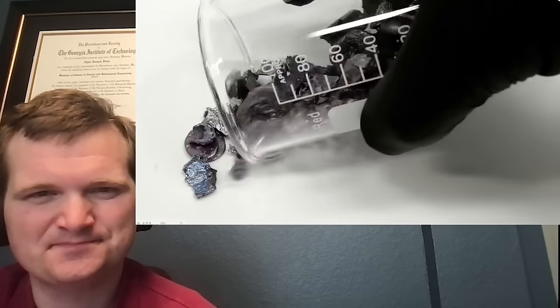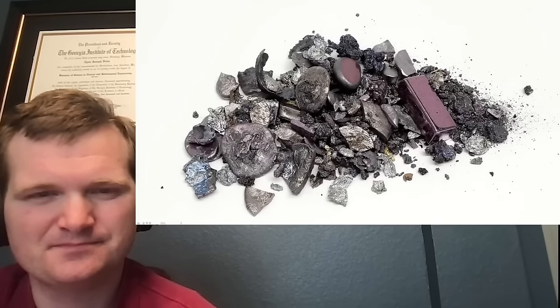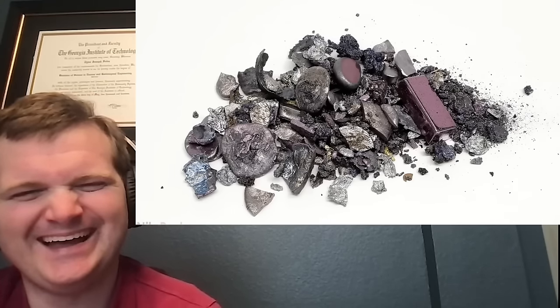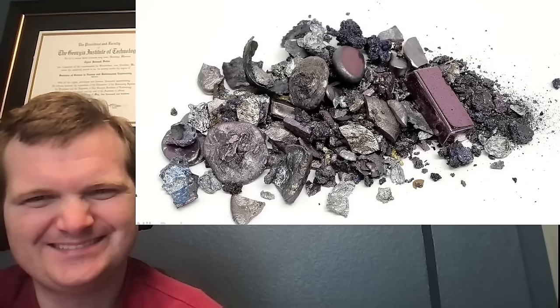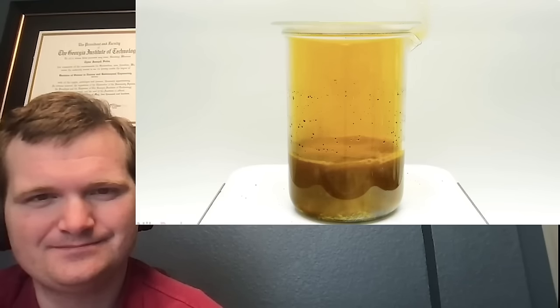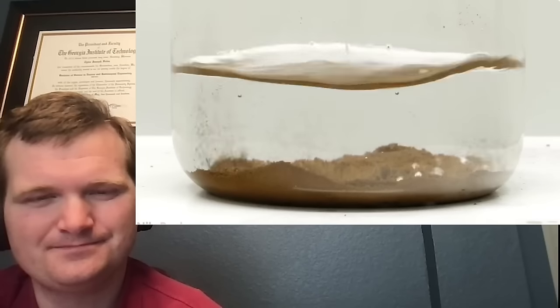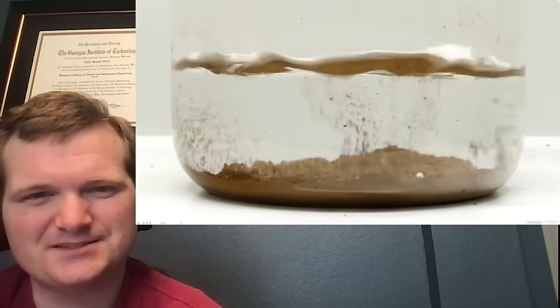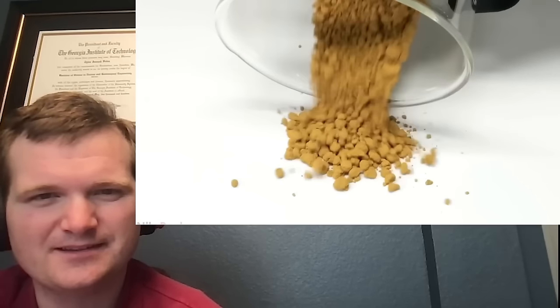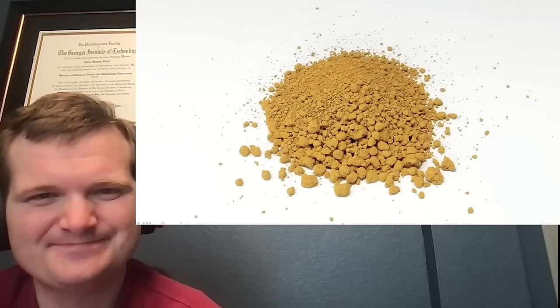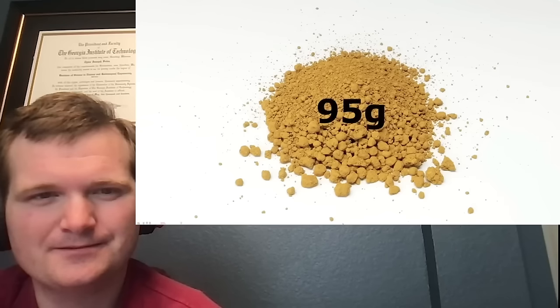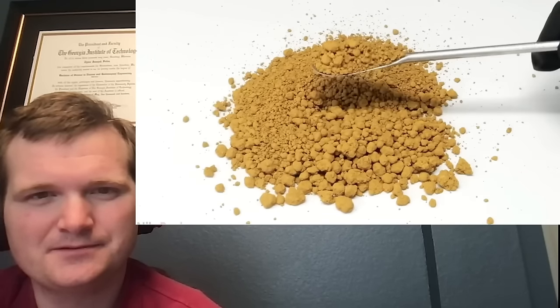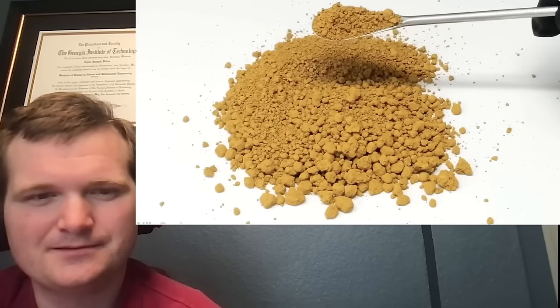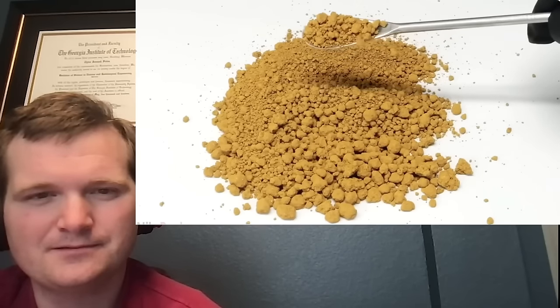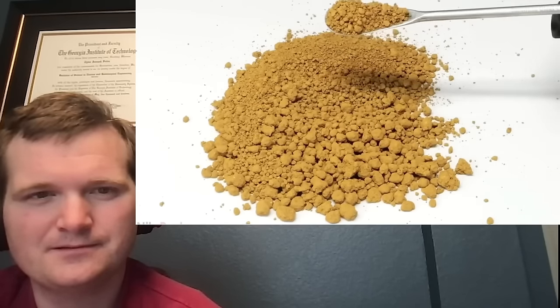This is because in all of my random attempts, I had apparently used all 99.99 grams of it, and it was now just a bunch of random trash. This was kind of a huge pain, but I didn't really have a choice, and I just quickly redissolved it all in a bunch of acid, and I processed it in the same way as the original gold bar. Then after a couple days of panning and work, I had some nice and crispy gold powder, except when I weighed it, it was only 95 grams. This meant that I'd somehow lost about 5 grams of gold along the way, and this made no sense to me because I'd been extremely careful, and I thought that I'd collected absolutely everything.